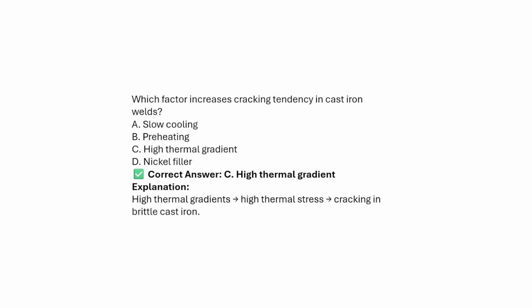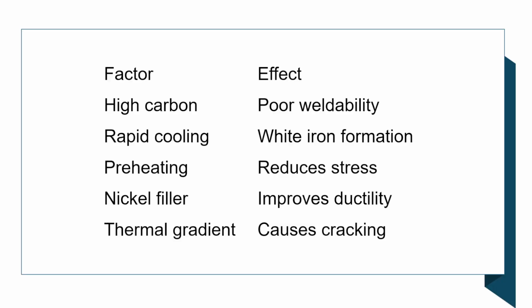Which factor increases the cracking tendency in cast iron welds? Slow cooling, preheating, high thermal gradient, nickel filler. The answer will be high thermal gradients. High thermal gradients mean high thermal stresses, causing cracking in the brittle cast iron.